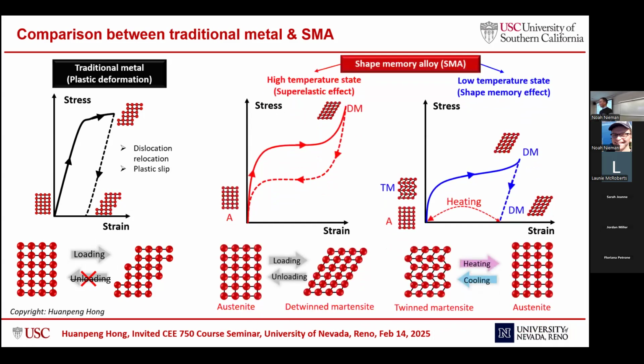However, for shape memory alloy, in the high temperature state and the low temperature state, it will be in different phases. In the high temperature state, it will start with the austenitic phase. It's a different phase, which is stable at high temperature and low stress. If we keep loading it to some point and then unload it, it will go back to the original location. That means it can recover all the inelastic strain and dissipate some energy. So the phase transformation from austenitic phase to detwinned martensitic phase is completely recoverable, loading and unloading.